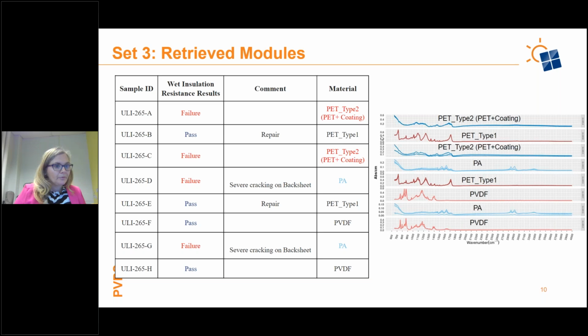Additionally, we got a set of three retrieved modules. These were all retrieved from the Florida, South Carolina region of the US. What we saw interestingly is two modules that we'll talk about in a bit, but they were PET type backsheets with cracking, and they were repaired modules. They were also able to pass the wet insulation resistance test after they were repaired. There were two polyamide backsheets that were not repaired and failed the wet insulation testing as well.